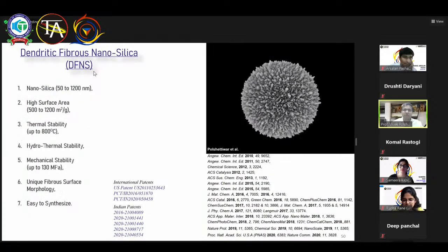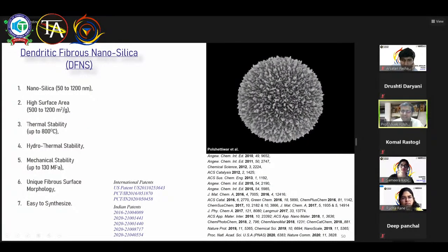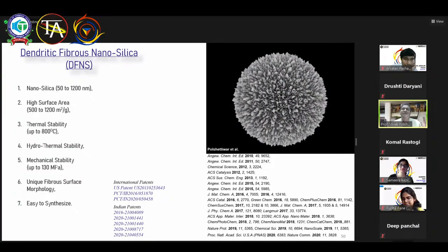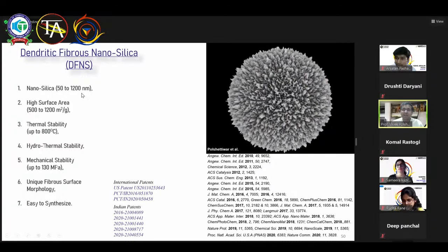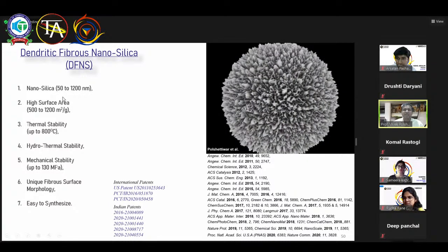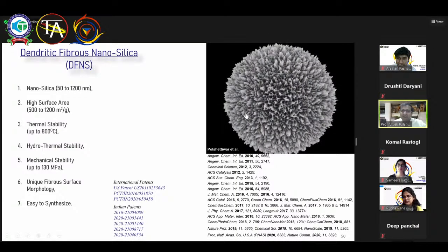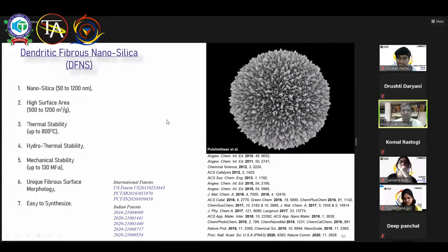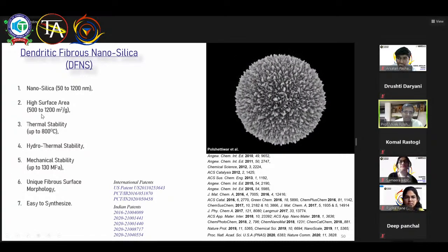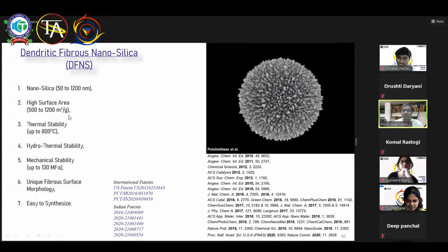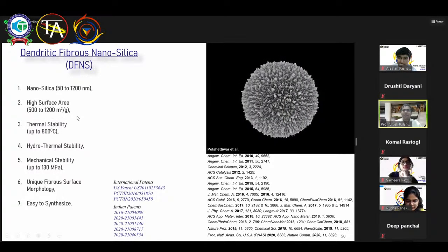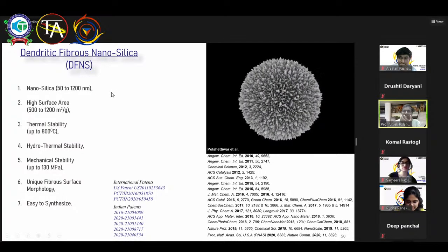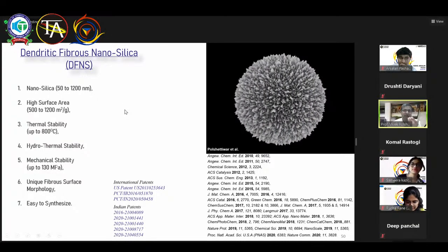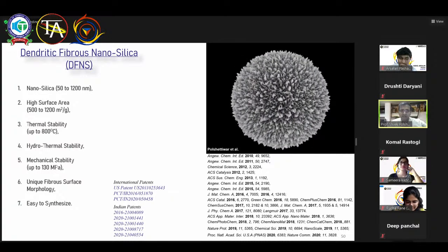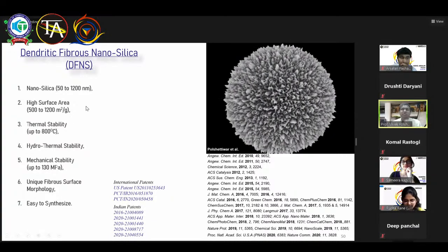So first thing, we need a catalyst support. In our lab, we developed this support. This is called dendritic fibrous nanosilica. This is ideally sand on the beach, but sand at a nanoscale. Scale is 50 nanometer to 1200 nanometer. I get 50 to 100, 100 to 200 different sizes based on the need. They have this dendritic fibrous morphology, and that's why we call them dendritic fibrous nanosilica, DFNS. They have excellent surface area, 500 to 1200 meters square per gram. 500 meters square per gram is like if you take 1 gram of this nanosilica powder in your hand, it's like a football ground in your hand. That's the high surface area you can achieve by simply taking 1 gram of material.